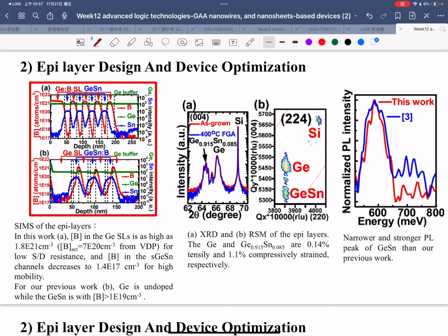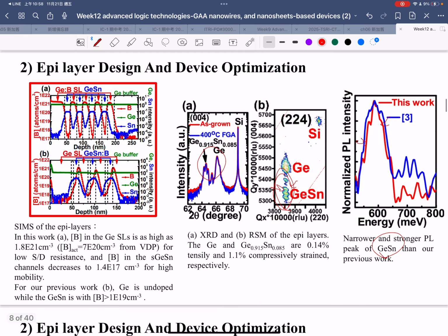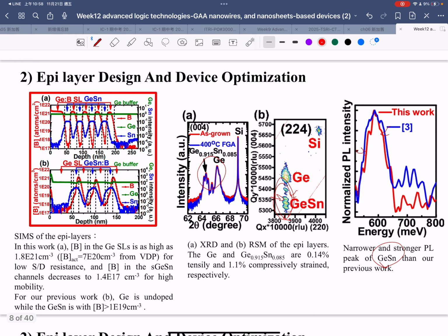Okay, so this is their epi layer design and device optimization. This is their germanium. For Raman, for PL, they have a narrower and a stronger PL peak, and then this is SEM. This is the XRD. They have very good, the distribution is tight and small. It means the quality of the germanium or the epi layer is good. If the width is large, it means the crystallization is not good enough. So from this XRD, that means they have very good germanium.